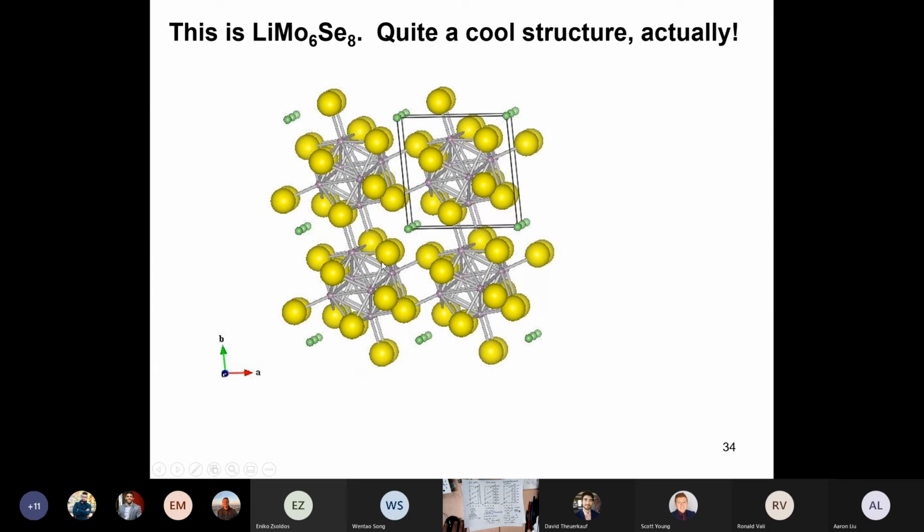Now, because these holes where the lithium can go are so massively huge, this particular structure can accommodate things like zinc and lead and big, massive cations. So it was used as a positive electrode material for magnesium intercalation and magnesium batteries. And it worked very well. The other thing about this is that this class of materials was discovered by a guy named Roger Chevrel in France, and they're called Chevrel phases.